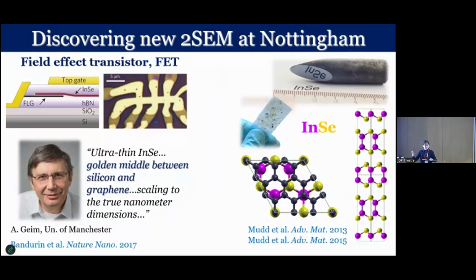We discovered we could get electron mobility larger than any other 2D silicon or graphene transistor. The graphene transistor has an issue because graphene doesn't have a proper gap, so you cannot switch the current on and off. And so this led André Geim to comment that we have found a semiconductor that is the golden middle between graphene and silicon.